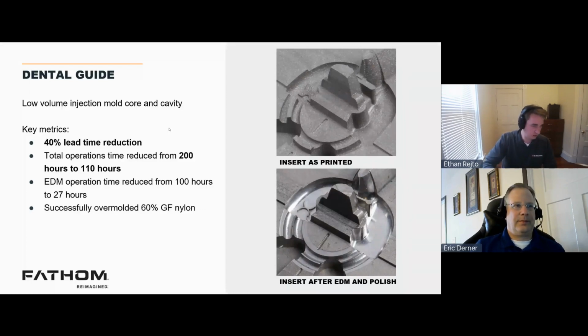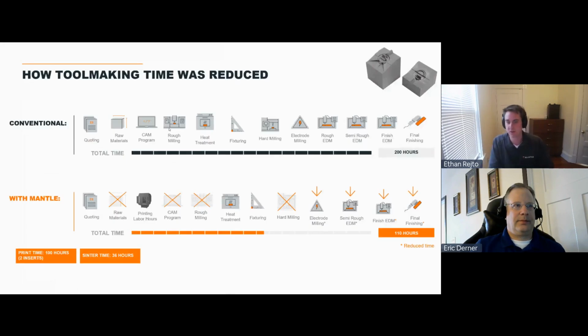So looking at this again, what are the steps they're able to remove? We were able to remove the raw material sourcing, their CAM programming, of course, all the rough milling. They did heat treat this. This is an H13, so they heat treated up to about a 50 HRC. They did some fixturing. They had to do less electrode milling because they were doing less EDM work now. And then they just did some final EDM work and some final finishing. So from 200 hours of work down to 110 hours.